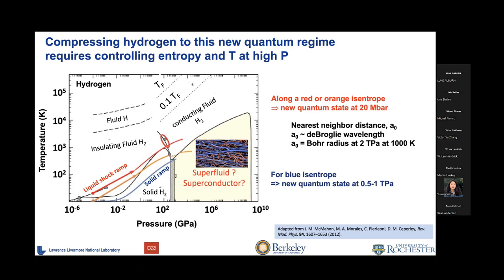And so here are a bunch of examples. We did early experiments a few years ago, where we take liquid deuterium and then we ramp compress it. We launch a shock wave and then we ramp compress it. It undergoes an insulating to conducting transition. Notice it gets pretty hot. And so it's not really clear that it'll ever reach this, even by the time you get to higher pressures. So that would be pretty hot, that'd be hard to do. So we're developing ways to get to lower and lower temperatures, so that we keep the material solid and access this much lower temperature region. So that's a major strategy of what we're doing.